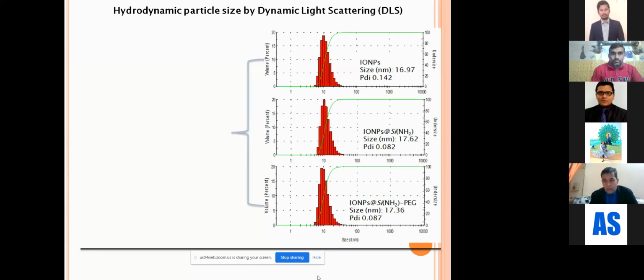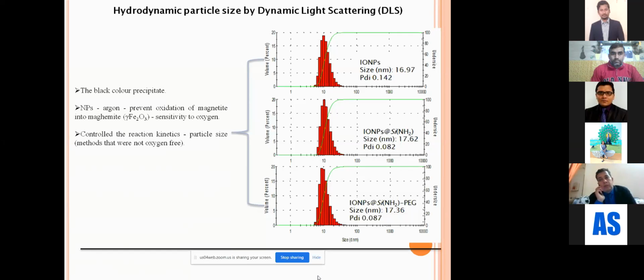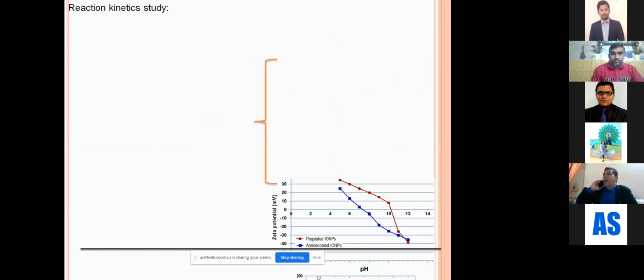And when we tried developing the coating, the functionalization in the form of amine or with the help of a polyethylene glycol kind of polymer, the size range changed only a little, not so much that we are not able to utilize it. So the size is very important when you are developing these particles. This is the dynamic light scattering graph. We are able to see the average size range of the nanoparticle. You could see the size range for the iron oxide nanoparticle after optimization, we will see what has happened to that.